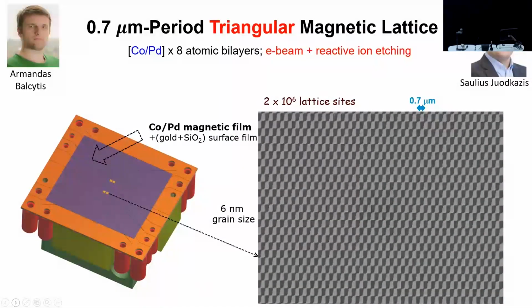Okay, so this was some work, Saulius Juodkazis, and student Armandas Balcytis prepared a beautiful structure here, which is a structure needed to produce a triangular lattice. The period here is just less than a micron, it's just 0.7 microns. We have something like 2 million lattice sites. We use 8 atomic layers, bilayers of cobalt palladium with just atomic thickness. And this enables us to have very small grain size and to produce very precise structures.